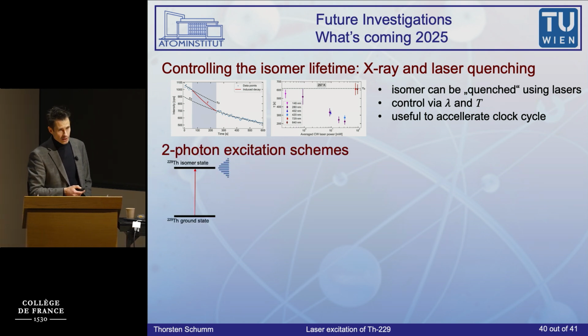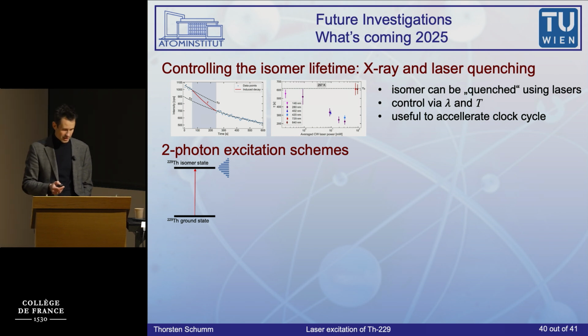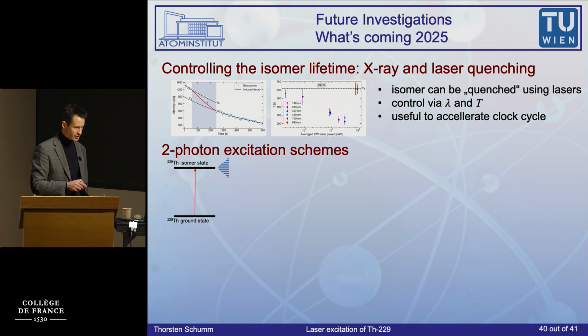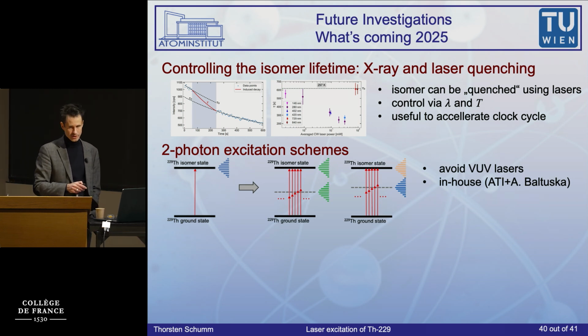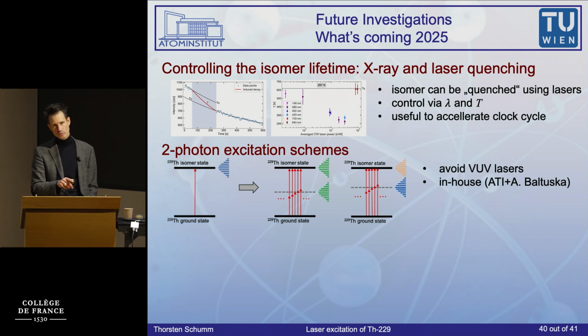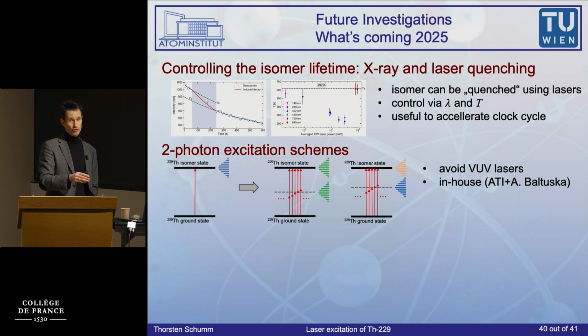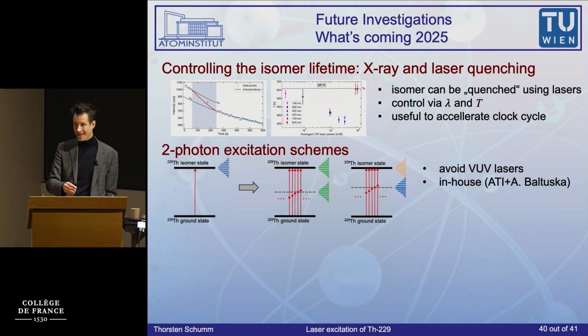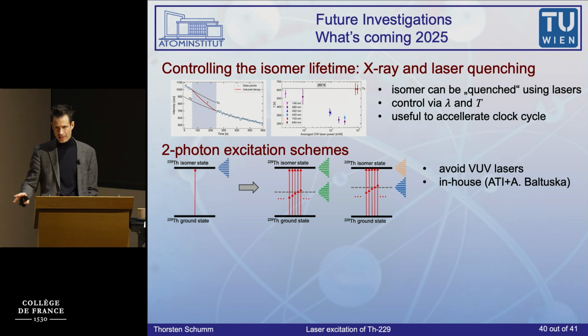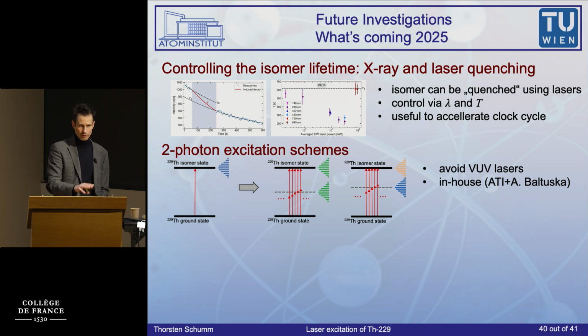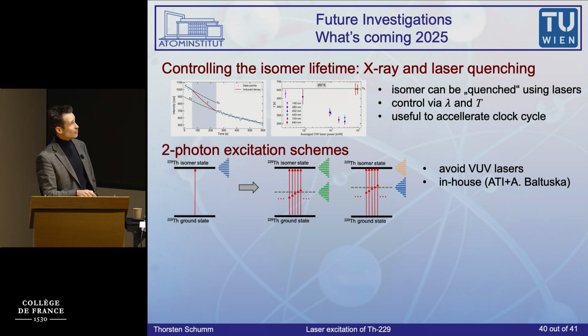The second thing is, I said I love lasers, but 148 nanometers is really not a good wavelength to work with. At the moment, what we're doing is we're resonantly exciting from the ground state to the first excited state in a 1-photon transition. What we would like to do is to do this in a 2-photon transition, where both of the photons would be at least below 200 nanometers, because then they would travel in air. Building a laser table with light that doesn't travel in air is really not fun. So we try to avoid this by playing with 2-photon excitation schemes.